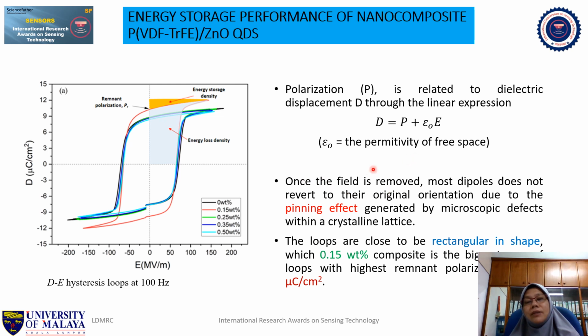So once the field is removed, most dipoles will not revert back to their original orientation because of the pinning effect coming from microscopic defects within the crystalline lattice. So from this hysteresis loop, we can obtain remnant polarization, which occurs at zero electric field, and also energy storage